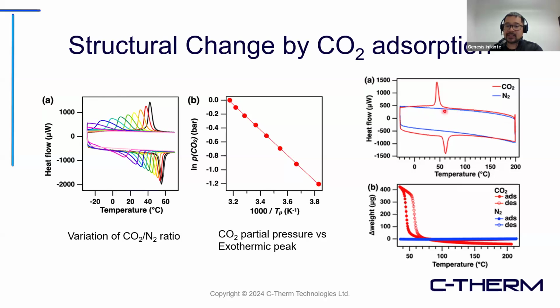So it really tells you that the MOF doesn't interact with nitrogen at all, so there's not a lot of thermal event going on there, but it does selectively adsorb CO2 on the surface. This shows the weight change in general, mass loss and mass gain, depending on the gas. You can see again no gain during the adsorption and desorption steps for nitrogen, but then there's the cycle between gain and loss of CO2 within the system.